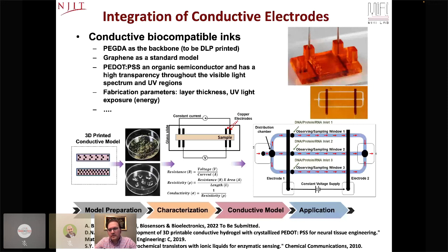And then we looked at the literature. We found that PEDOT:PSS is a good combination. It's an organic semiconductor that people use with PEG. And when you mix it with PEG, it has high quality conductivity. We have been optimizing the fabrication process and learning how we can control the conductivity property. This is ongoing research, which I'm not going to show more details on, but this is something that we are interested in adding to our system.